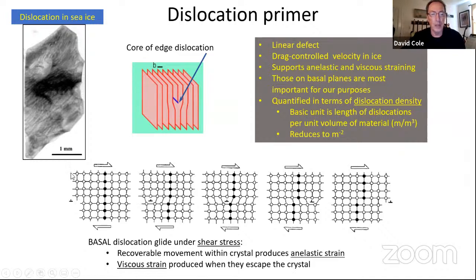The dislocation would be, here's our extra half plane under a shear stress, and with the breaking and reforming of atomic bonds, this extra plane and our dislocation core that we're dragging along moves through the crystal. Now, if it just moves part way and stops, it's under the influence of some internal stress fields that would in fact cause it to move in the opposite direction if we were to remove that applied shear stress. If there's enough time for the dislocation to move all the way to the end of the crystal, that gives you one increment of permanent or viscous deformation. But the case where it remains in the crystal and rebounds under the internal microstructural stress field, that's the process that gives us this anelastic behavior.